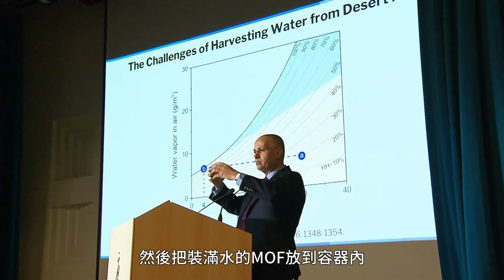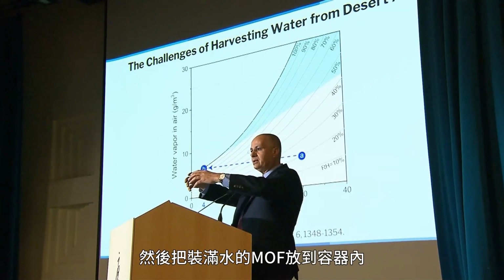And then I take this MOF that is filled with water and I put it in a container. I close that container and expose it to sunlight. The interior of the compartment will heat up, water comes out of the pores and condenses. So now I have created a humidified environment, and in so doing, I only need to decrease the temperature by a few degrees to get the water out, okay?